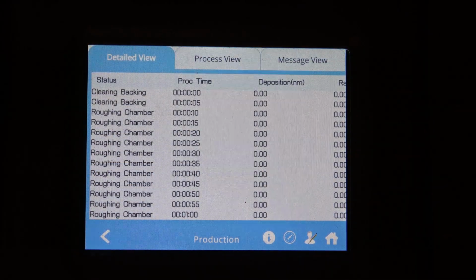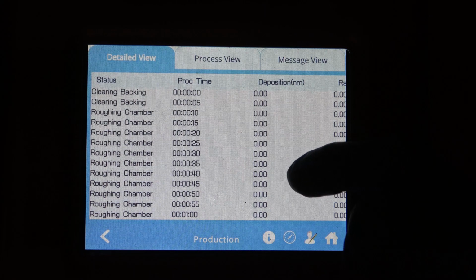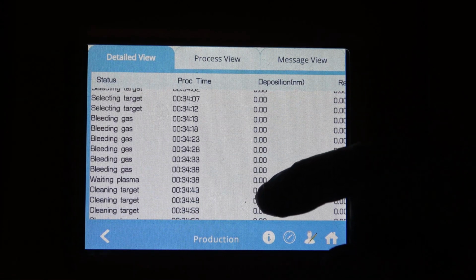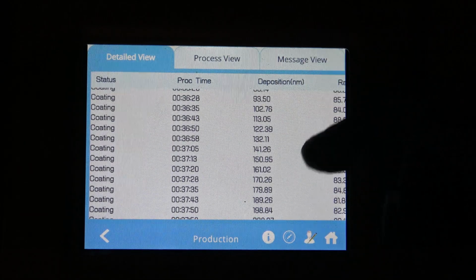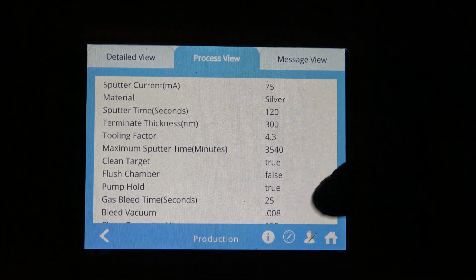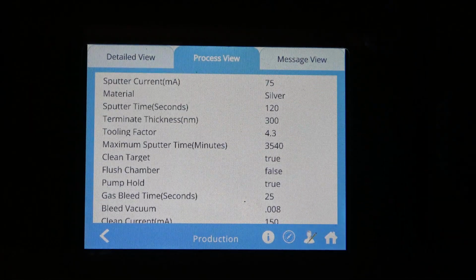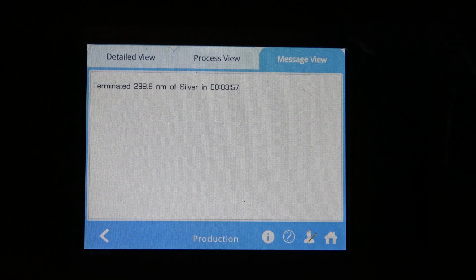So here's a silver process that I ran. So these can be outputted to a thumb drive. So this gives you a detailed view of the pump down cycle. Select target, system tells you what's going on. I use pump hold a lot. Bleeds the gas into the chamber, waiting for plasma, cleans the target, stabilizes, coats the target, and then terminates the process. That's the detailed view. You have process view, tells you exactly what parameters you're running with, and then message view, which is really not terribly exciting.